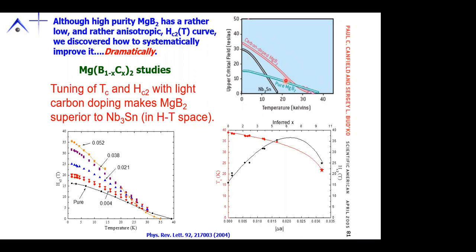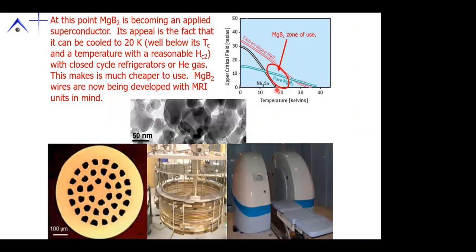And perhaps more importantly, we have this region at around 20 Kelvin, which in subsequent years has become known as the MgB2 zone of use, where we can actually have superconductivity where Nb3Sn hasn't even turned on. We can have superconductivity at the temperature a very simple Displex, a closed cycle refrigerator, can cool us, and we can have Hc2s as high as maybe 10 or 15 Tesla.